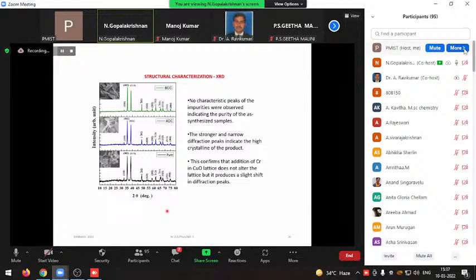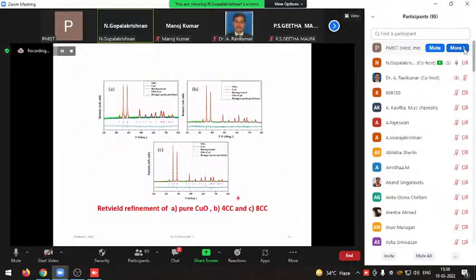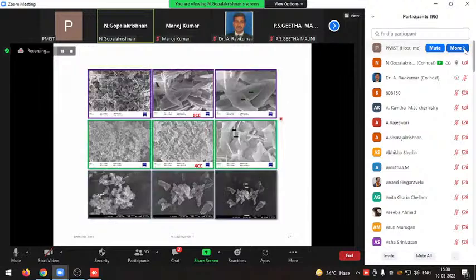Then we subject it to different characterizations. This is our XRD, also with 4 chromium doped and 8 chromium doped. We also give the explanation of why the characterization changes. We give a very good explanation. Then we follow Rietveld refinement and measure the lattice parameters. Then, yeah, this is the important thing.